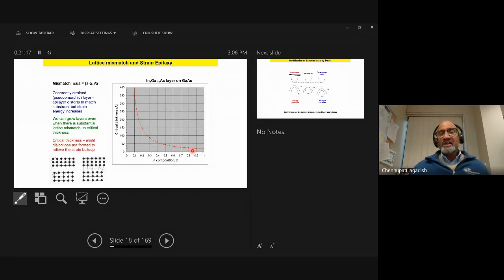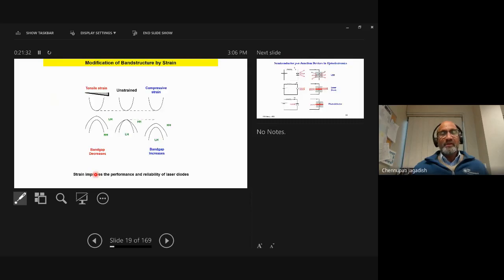So why are we interested in strained layers? Again, this shows the critical layer thickness, and if you exceed that, you create the dislocations. Dislocations are nothing but missing atoms or excess atoms, depending on what you're looking at. So here's a case where you do not have any strain: the conduction band is here, and the valence band has a heavy hole and a light hole, as you can see. But once you introduce compressive strain, you lift the degeneracy between the heavy hole and the light hole, and also increase the band gap of the semiconductor.